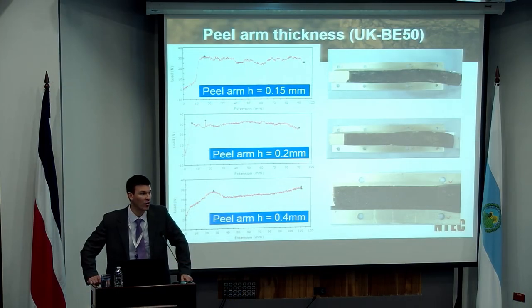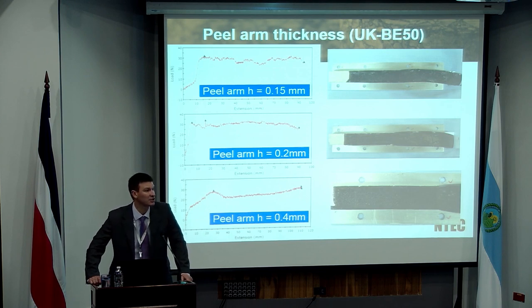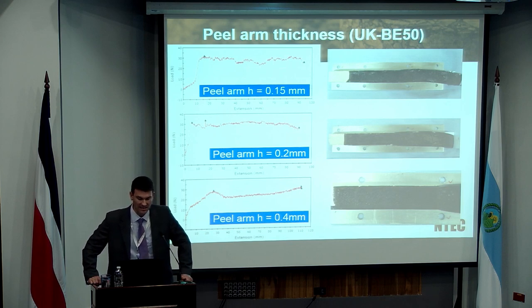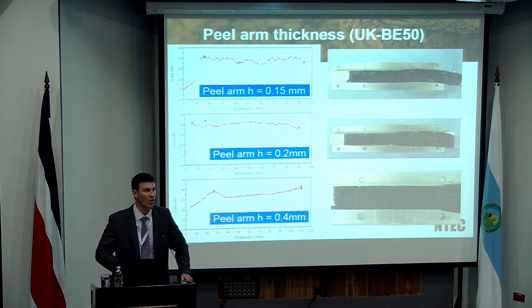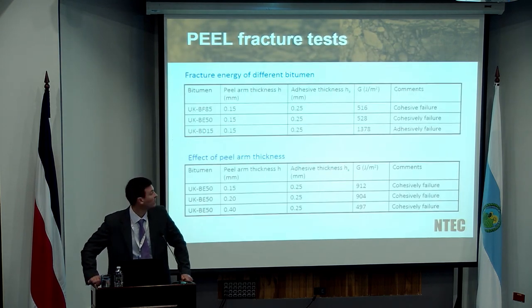And the first thing to notice is that although the failure mechanism, and you can see the failure mechanism because what you would do is once you've peeled off your aluminium peel arm, you can see where the failure has occurred. It's either occurred within the bitumen itself, in other words, it's a cohesive failure, or it's occurred at the interface between the aggregate substrate and the bitumen, which is a more adhesive failure. So the failure mechanism is exactly the same. That doesn't change. What tends to change is the actual values in terms of your fracture strength or your force to cause failure. And that graph just quickly summarizes.